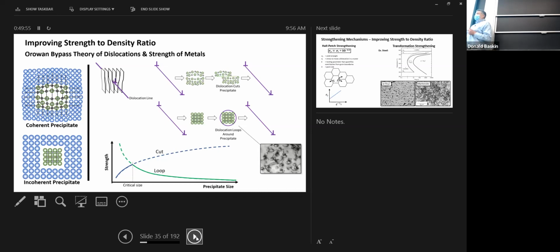Right, and this is actually what it looks like. This is a transmission electron microscope micrograph that shows dislocations wrapping around precipitates. This is real. And when you get to this size, it takes less and less energy to get the dislocation to wrap around and move past. They call it looping, loop around the precipitate and keep going. And then the strength of the material goes down. So there's an optimum size where you're using this cutting mechanism as long as you can until the precipitate gets too big. It's an optimum size right here where the threshold between cutting and looping takes over. And this is where you want to artificially age the precipitate so that they're this size right here.